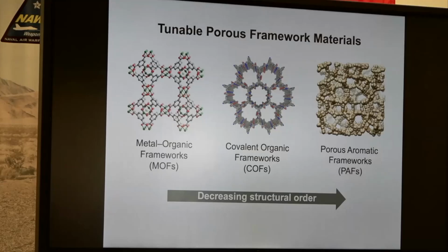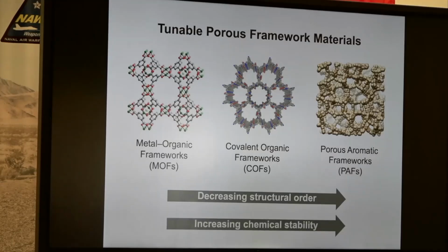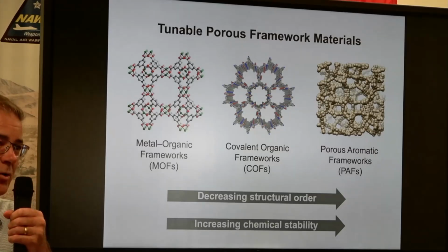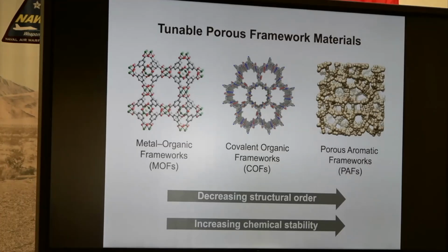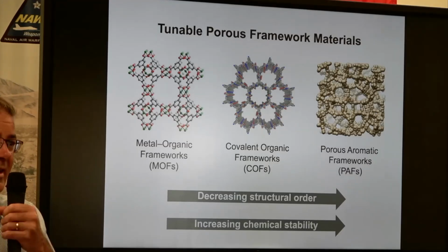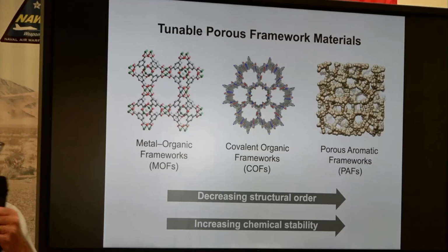But there is an advantage to the amorphous network solids, or PAFs, in that these are incredibly chemically robust. These can tolerate strong acid or strong base. So you can expose these to 6 molar acid and there's no problem with degradation of the material, whereas that is not true of COFs or MOFs. And so that's going to be an advantage if you're trying to separate metals from an acidic waste solution.